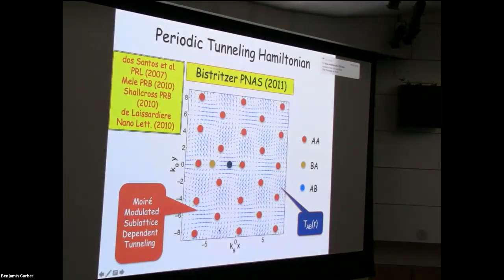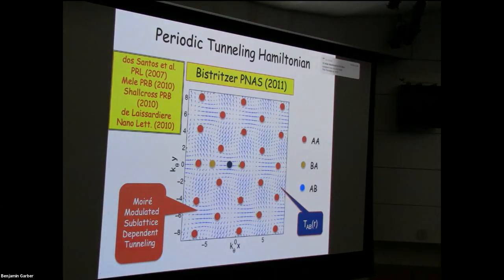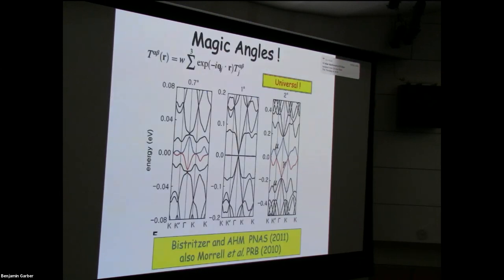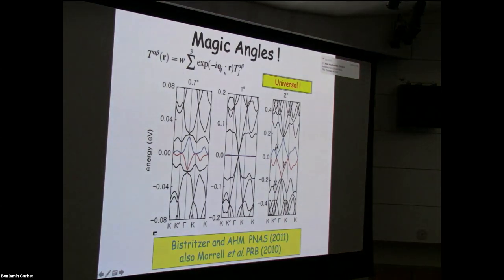So each element of the 2x2 interlayer tunneling matrix has a natural position dependence like this. And everything is characterized in the simplest approximation by a single number, which is the strength of this interlayer tunneling. And so when we were looking at two layers of graphene that are coupled in this way with Rafi Bistritzer, this is sublattice dependent interlayer tunneling written in a certain way here, but all it's saying is that the interlayer tunneling has a periodic spatial pattern.